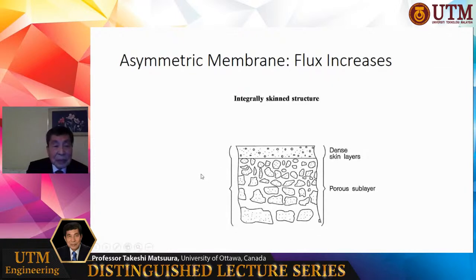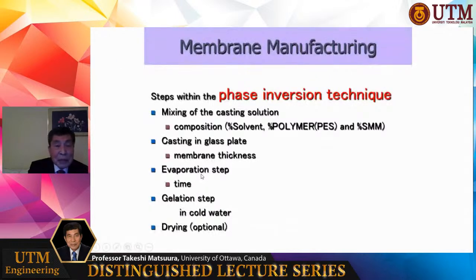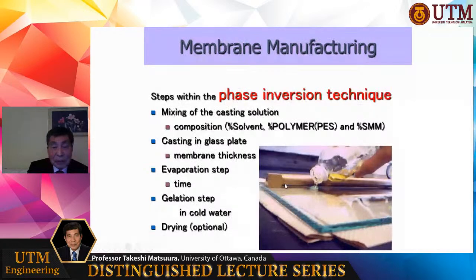So how can you make this kind of structure? There are two methods. One is the so-called phase inversion technique. In this technique you just make a polymer solution. Polymer is dissolved in solvent. By the way, polymer means, let's say, something like plastic material. It is dissolved in solvent, and cast on top of some supporting material, in this case a glass sheet. This is the polymer solution. It is cast on a sheet, and then it is dipped into water.